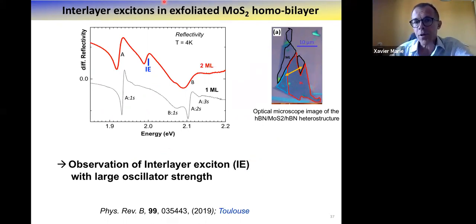So let us start with very basic exfoliated MoS2 homo bilayer. You use mechanical exfoliation. Statistically, when you transfer, you have monolayer, bilayer, whatever. And then you encapsulate your bilayer and you do a simple reflectivity contrast experiment, differential reflectivity as a function of energy. So for the monolayer, I just recall that we observe, as already presented, the A exciton, the B exciton, here the B 1S exciton. You can even observe the excited states 2S, 3S, whatever.